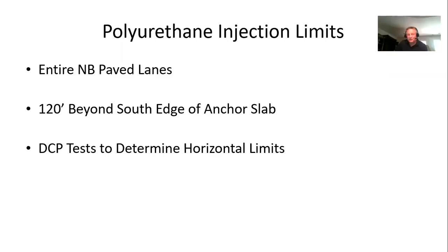Actually, what we did was we looked at the profile, and we could see where that profile was dropping off, where it shouldn't be, and so we determined we had to go back about 120 feet. We didn't have a whole lot of geotech info back that far, other than the wall borings, which were kind of along the side. And so what we did was, within this area, we used the DCP,